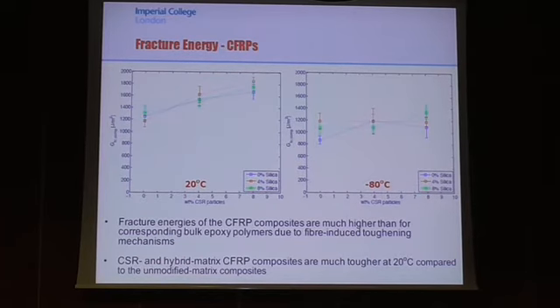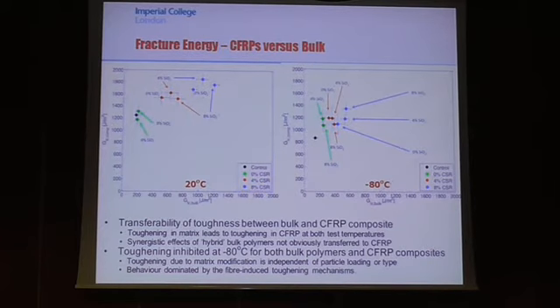The last point to note as well is that, like in the bulk polymers, the CSR particle composites are tougher at room temperature than at minus 80 degrees. This should be no surprise. One of the ways to look at this is to plot the bulk material fracture toughness versus the composite material fracture toughness, and these dashed lines are slopes of 1 to 1, indicating that if your data lies along these slopes, there's a perfect transferability of toughness.